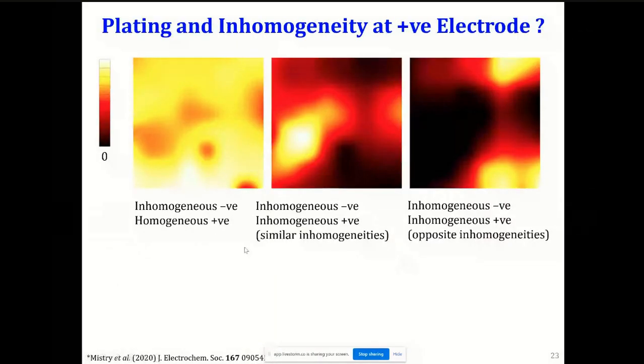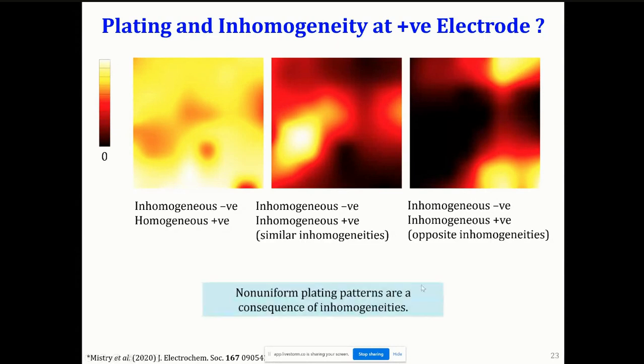Now, the video I showed on the previous slide had an inhomogeneous negative electrode and a homogeneous positive electrode. If you keep the same inhomogeneity profile, but you now make your positive electrode inhomogeneous, it's going to give rise to a different profile. If you make the positive electrode inhomogeneous, but now flip it, so you align the low porosity spots with high porosity spots, you are going to see a totally different plating profile. And often you look at the experimental data and you see all these irregular plating profiles. It hardly ever plates uniformly at the surface. And it's partly because these inhomogeneities, which are aligned, partially aligned, or misaligned, give rise to these patterns, which on the face of it look random.